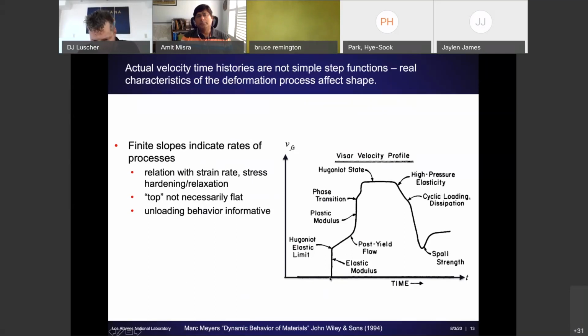So, if you could accurately resolve that initial rise, the time of arrival will be related to the longitudinal wave speed, which, if you know the density accurately, is connected to the elastic modulus. Of course, the height that we've mentioned already is related to the Hugoniot elastic limit, which is an indicator of the transition stress from elastic behavior to triggering some inelastic mechanism. That's usually, in polycrystalline or single crystal metals, dislocation-accommodated plastic flow, or plastic deformation. Then we can look at characteristics of that plateau to understand something about the processes of hardening and evolution of dislocation behavior.